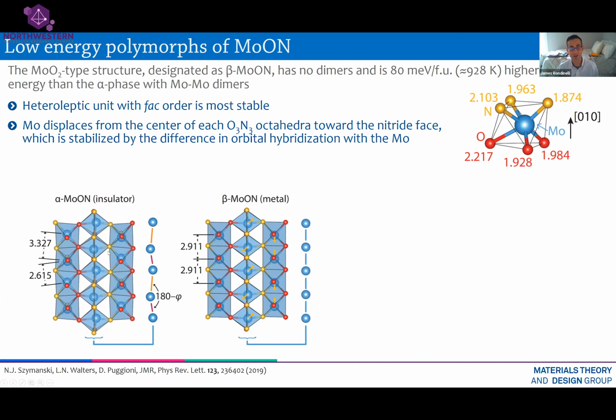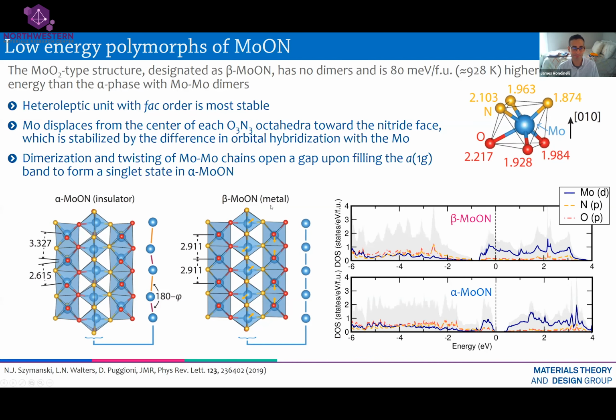So we have two phases which are competing with each other. One is a metal and one is an insulator. And the tendency towards this insulating state is dependent on this FAC ordering. So there is a strong driving force for this FAC ordering. And it's this combination of the heteroanionic character, having two anions, which makes molybdenum d1, that allows for the metal insulator transition in the compound.